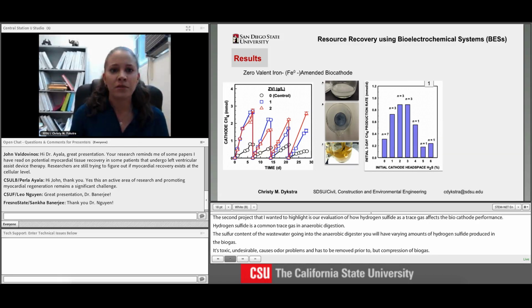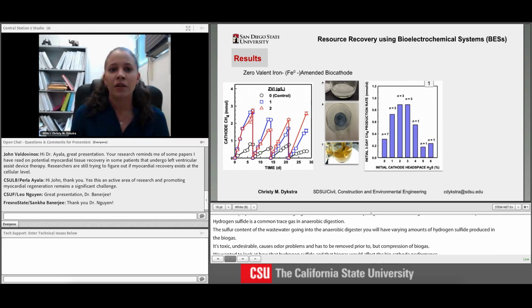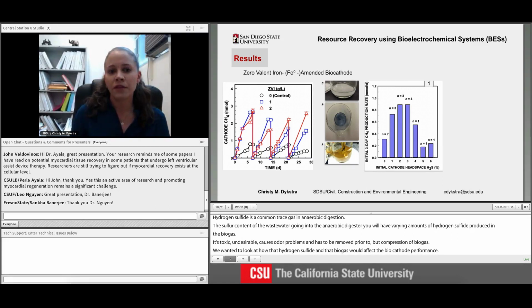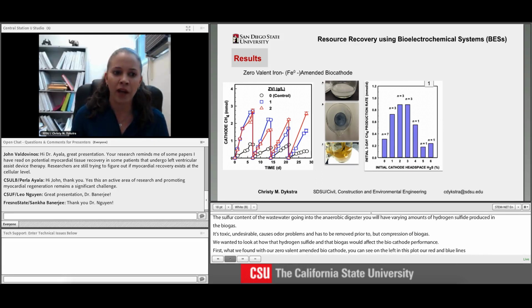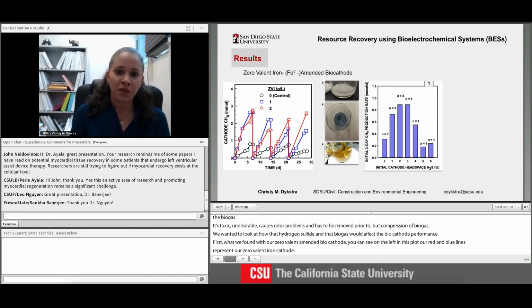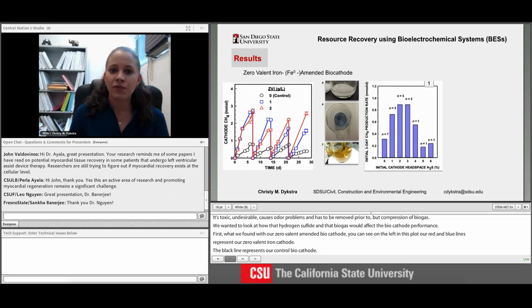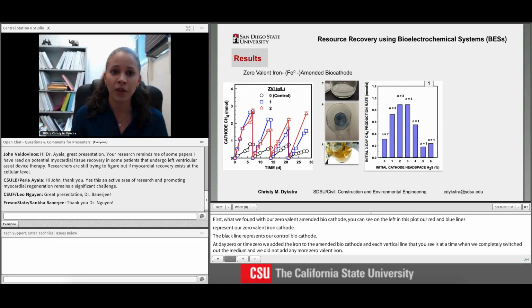So first, what we found with our zero-valent iron amended biocathode: you can see on the left in this plot, our red and blue lines represent our zero-valent iron amended biocathodes at 1 and 2 grams per liter, and the black line represents our control biocathode. At day 0, or time 0, we added the iron to the amended biocathodes, and each vertical line that you see is a time when we completely switched out the medium, and we did not add any more zero-valent iron. Yet, despite that, we see elevated amounts of methane production throughout over 4 feeding cycles without any more addition of iron.